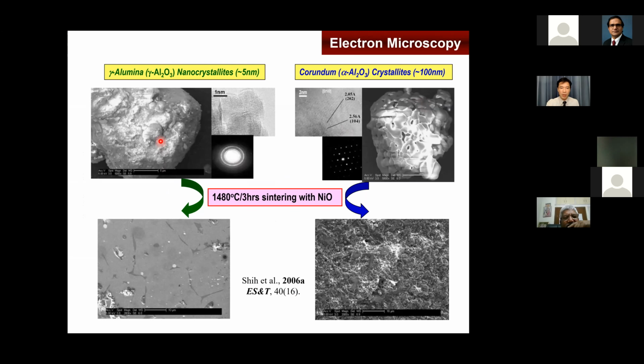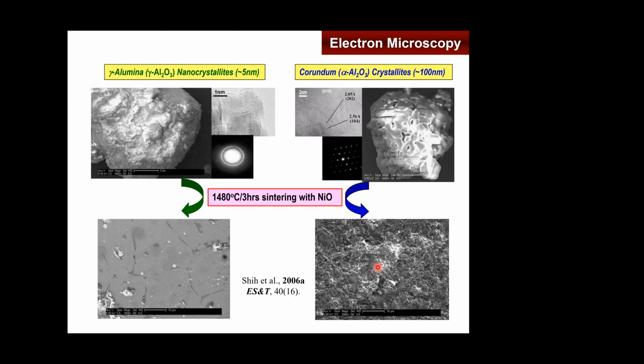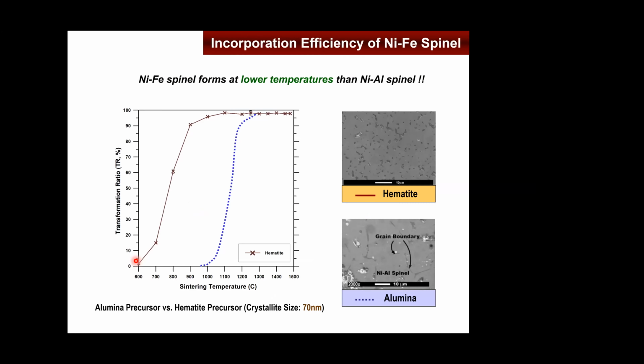For example, if I use gamma alumina to start with, then our product will be of large crystal, very well packed microstructures. But if I'm using the alpha alumina, what I actually end up with is a very porous microstructure. In fact, the nickel alumina spinel in the industry has been considered one type of catalyst. So if you want to make good use of your product as a later usable catalyst, you should choose alpha alumina to start with because it naturally gives you very nice porous materials at the end. But if you are aiming to stabilize your hazardous metal, then you want this kind of very dense, large crystal microstructure.